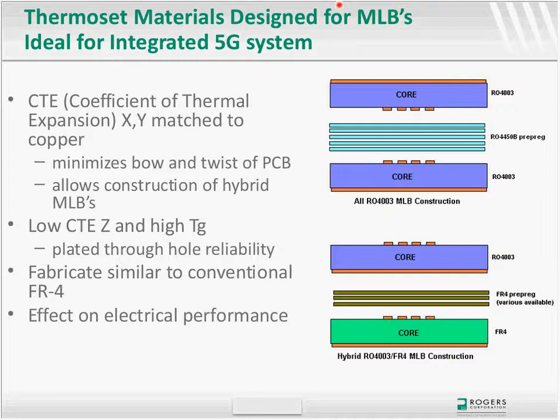So many materials in the traditional circuit board world are designed to be around 16, which is the value for copper, the copper foil that is used. So all the materials that are used in RF have that in mind. Some materials have significantly higher expansion coefficient, which can create a bow and twist situation. So that's one thing to look at in the data sheet and to take into consideration.